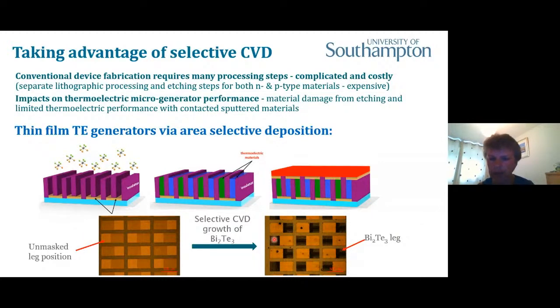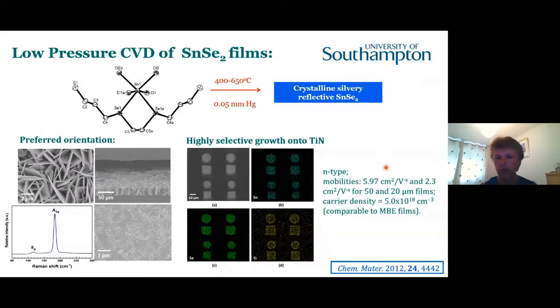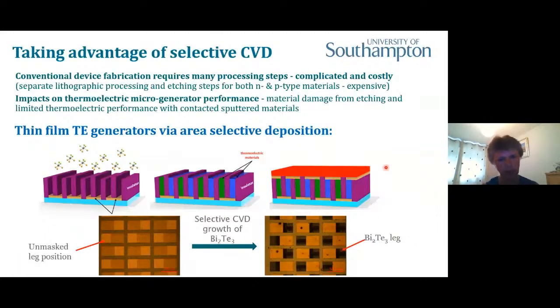the titanium nitride. And on this figure down here, we can see the black region is actually bismuth telluride on what was the exposed region. We will then mask that off, cover it, and unmask the next titanium nitride region to deposit the antimony telluride. And then we have these arrays shown in the cartoon graphic here of P and N couples to generate our micro device. So that's really what I wanted to say about the thermoelectric materials,